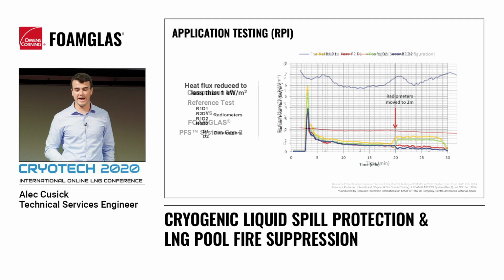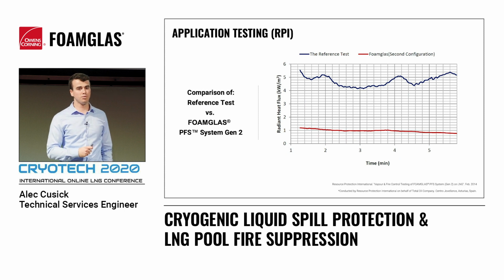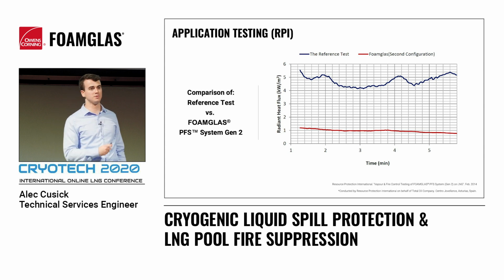And here you can see the average of all 4 radiometers plotted under steady state conditions for both the original reference test as well as the second PFS Gen 2 round of testing. And here you can really notice, when plotted on the same graph, just how drastic the reduction in radiant heat between the first and second round of testing was with our PFS Gen 2 system.